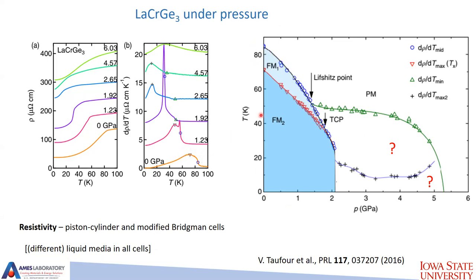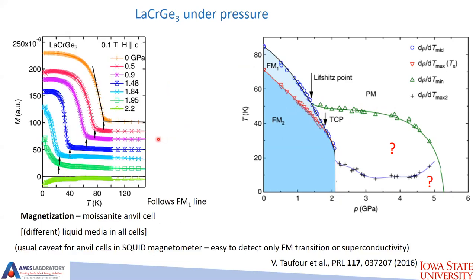Now, I need to admit that identification of this phase line from points like this was basically based on our prejudice from work on uranium cobalt 2 and other uranium binary compounds done elsewhere before, where not just transport but other measurements confirmed that there are two ferromagnetic phases. Anyway, here is the phase diagram. So it looks like there is another phase which is born after you suppress the ferromagnetic phase. And indeed, the transition becomes first order at some pressure. So we also did magnetization, and indeed, the ferromagnetic ordering temperature decreases when you apply pressure.